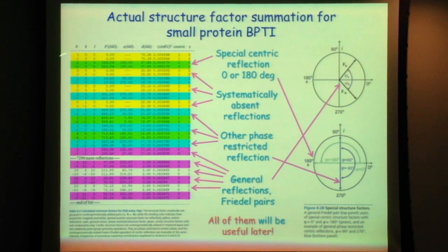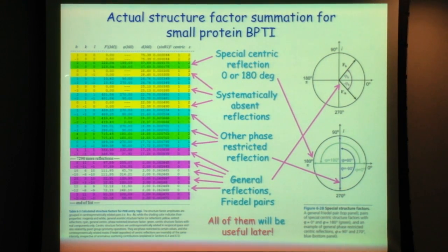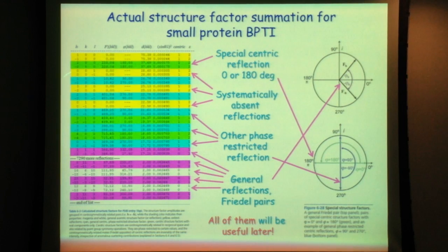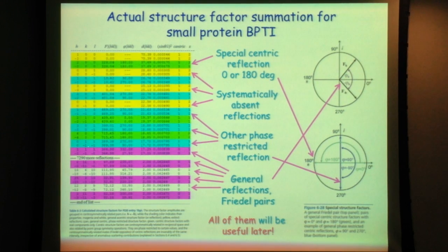Going out along the h-axis, here's 100 and its opposite reflection, we don't find a magnitude for that 100 reflection, although we do find a good intensity for the 200, but then we miss the 001 and so on. There are conditions that cause the magnitudes for these classes of reflections with odd K or L to vanish.